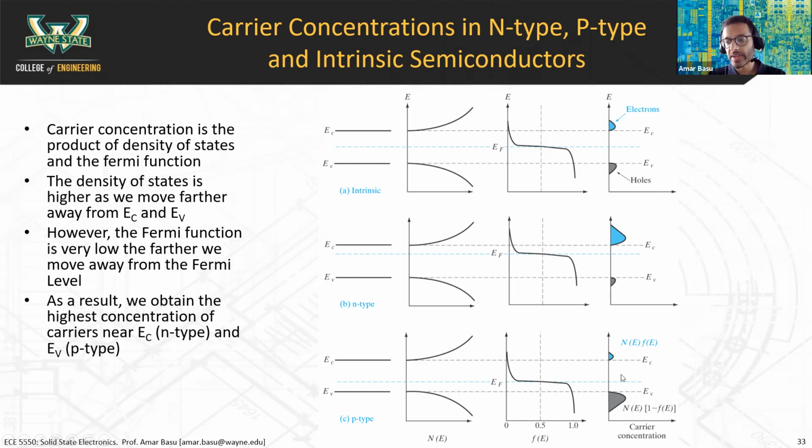This all basically came from moving the Fermi level upwards. In the p-type, it's just the opposite. The Fermi level is lower, close to the valence band, and that increases the probability of finding a hole in the valence band. I also want to look at what it does to the alternate carrier. If the Fermi level is close to the conduction band, large number of electrons, fewer number of holes. Okay, it's a subtle but important point.